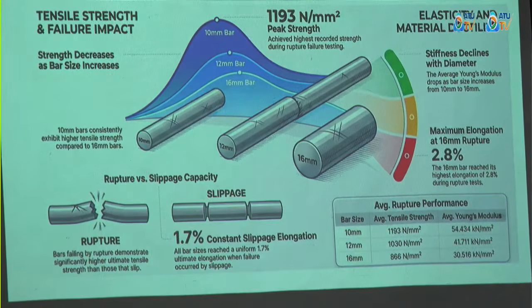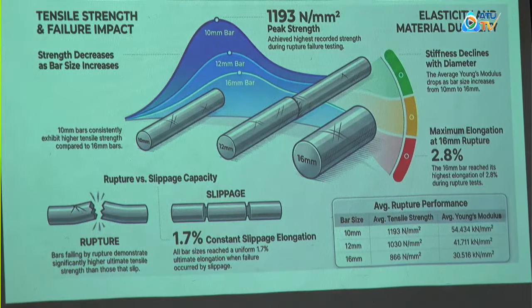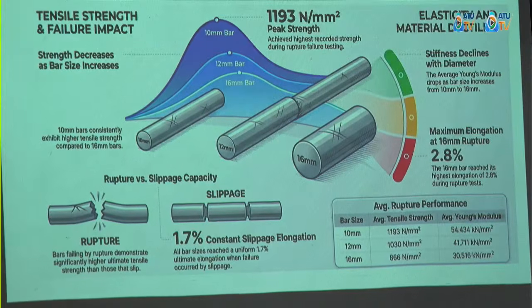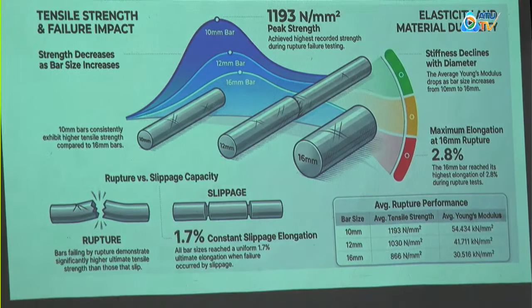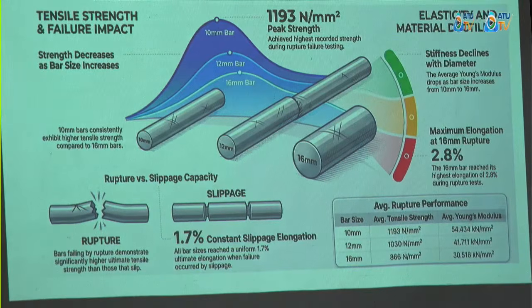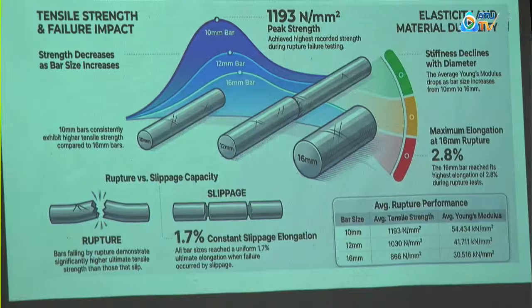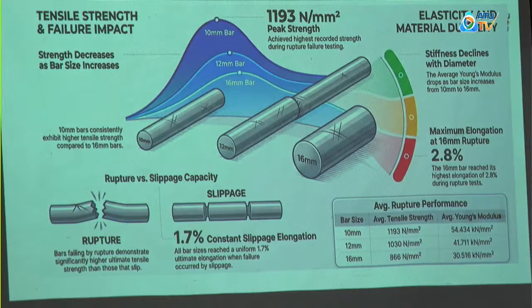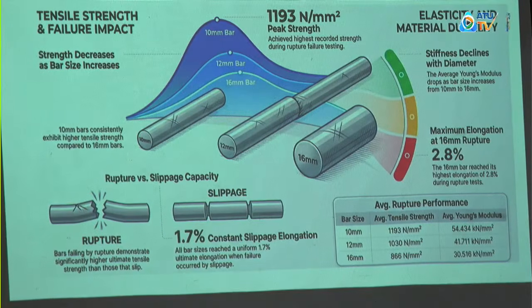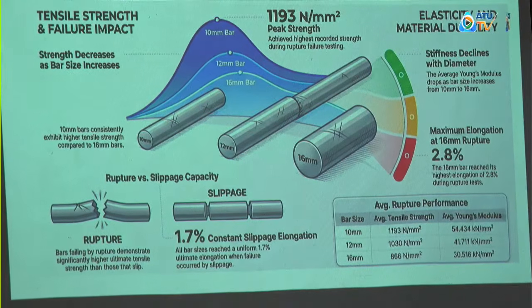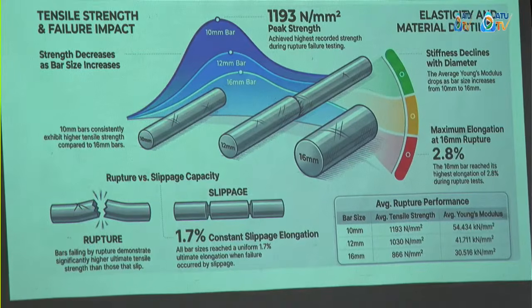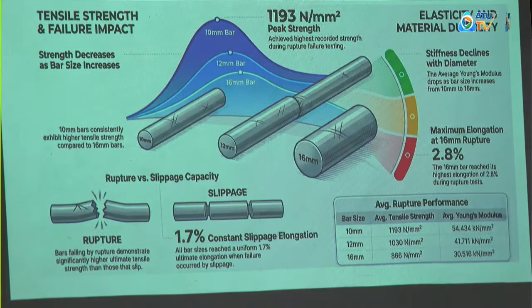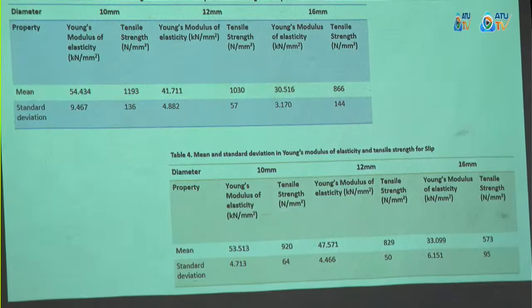Okay, so he tested 10 mm, 12 mm, and then 16 mm bars. What the researcher realized was that the strength of the GFRP bars decreased as the bar size increased. What it basically means is that the tensile strength of a 12 mm bar is higher than that of a 16 mm bar. We also see that bars failing by rupture demonstrate significantly higher ultimate tensile strength than those that slip. So if you pull the GFRP, you realize that the strength is lower when it slips.